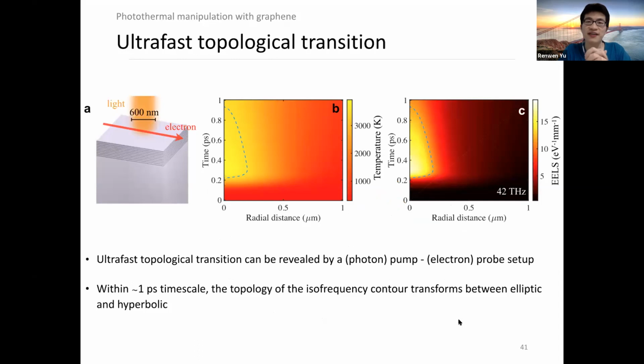So in order to show it's really an ultra-fast topological transition, here we are thinking about a pump-probe setup. So we are using an optical pulse pump and an electron probe. First, we calculate the spatial-temporal dynamics of the electron temperatures in graphene, and as a result of the electron temperature dynamics, we can calculate the electron energy loss spectroscopy of the probe electron, and we can see that we can have some very high EELS value in this region enclosed by the blue dashed curves. Actually, inside these blue dashed curves, we have the spatial-temporal region with hyperbolic isofrequency contour.